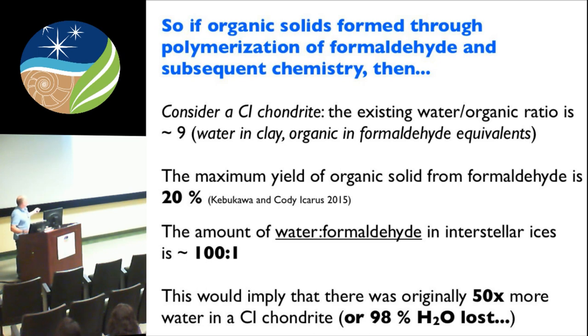What I mean by that is if you take a CI chondrite, a highly altered chondrite, the amount of water relative to organic carbon on a per carbon basis, at the atomic level, is on the order of 9. So the water's in clays and the organics are in the formaldehyde equivalent. So it's a rock, but it's a clay-rich rock. It turns out that Yoko was able to show, in a very straightforward way, that the maximum yield of this organic solid you could ever get out of formaldehyde is 20% because of competing reactions that degrade it.